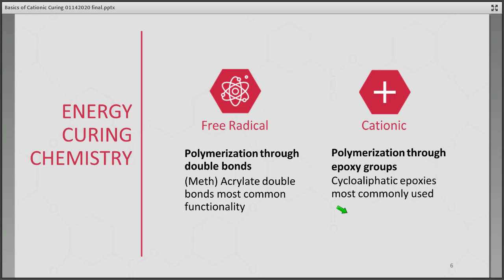Okay, let's compare free radical, because most people are familiar with free radical chemistry, with cationic cure chemistry. In free radical, you get the polymerization through double bonds, and it is usually acrylate or methacrylate double bonds that is the most common functionality. For cationic cure, you tend to get more commonly polymerization through epoxy groups. And in cationic cure, cycloaliphatic epoxies are most commonly used.